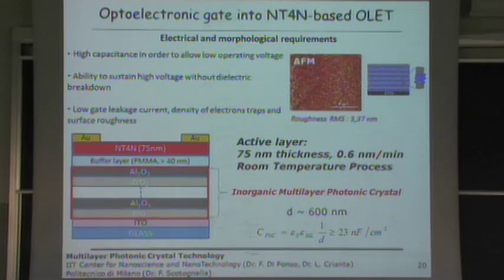We have a roughness of 3.37 nanometer. It is not bad, but anyway, we decided to put a buffer layer of PMMA on top of it in order to planarize even more the structure.